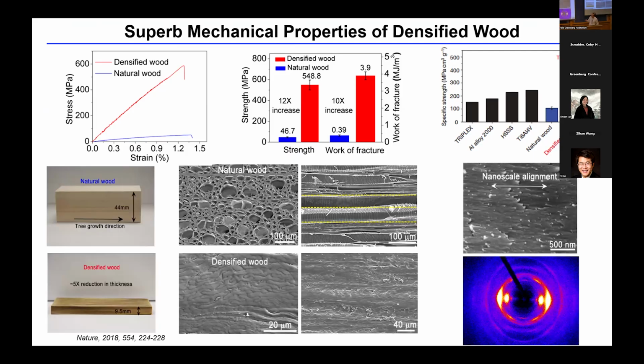And if you look at the structures, all the way you have these fibers, of course, not surprising. One of the keys is not to destroy those fibers here. So that's why JY mentioned today, you should not use acid to treat the wood because it will decrease the DP, degree of polymerization. So the longer the fiber, the better. So definitely don't destroy them.